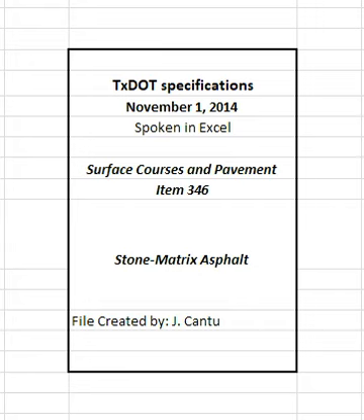1. If the engineer's laboratory molded density on any sublot is less than 95% or greater than 97%, take immediate corrective action to bring the mixture within these tolerances. The engineer may suspend operations if the contractor's corrective actions do not produce acceptable results. The engineer will allow production to resume when the proposed corrective action is likely to yield acceptable results.